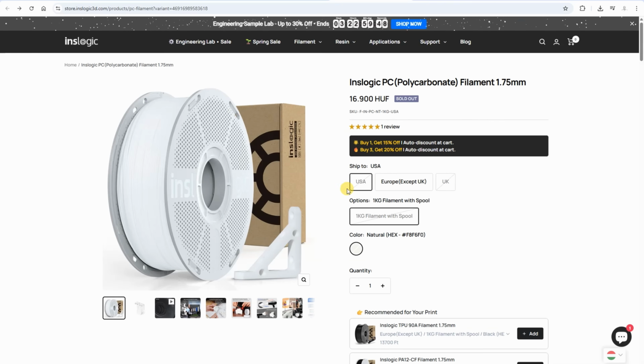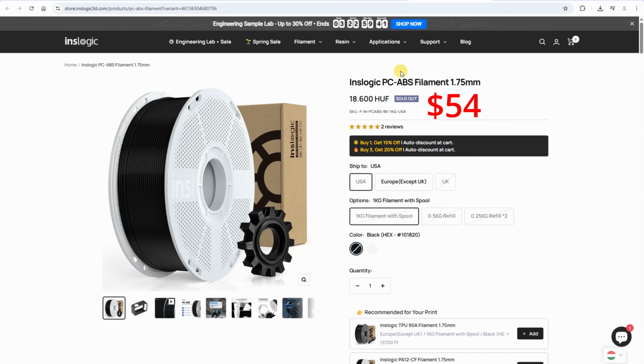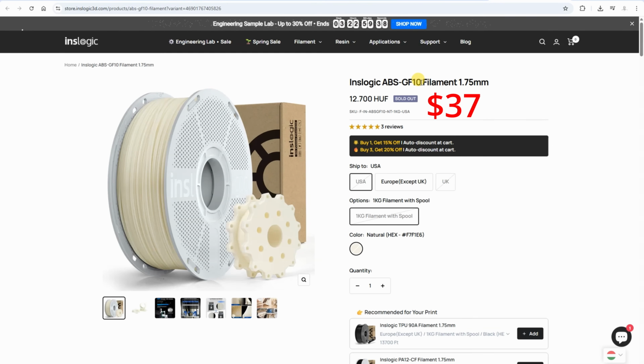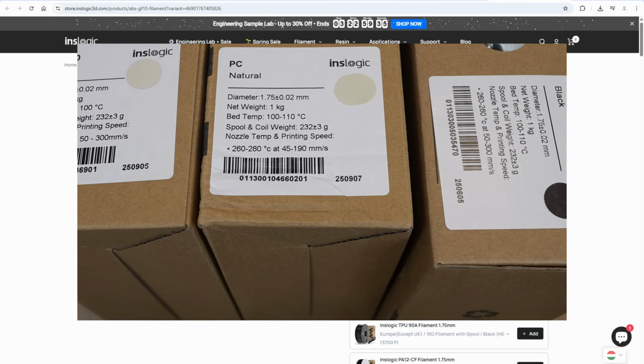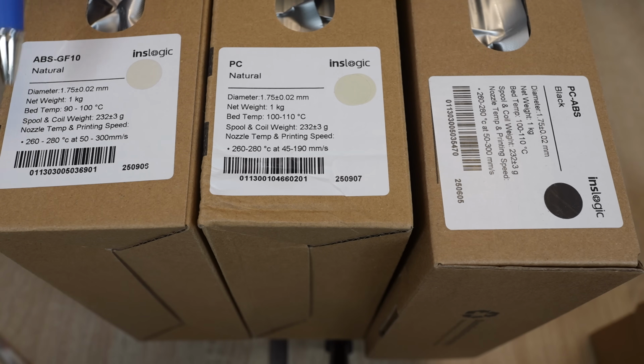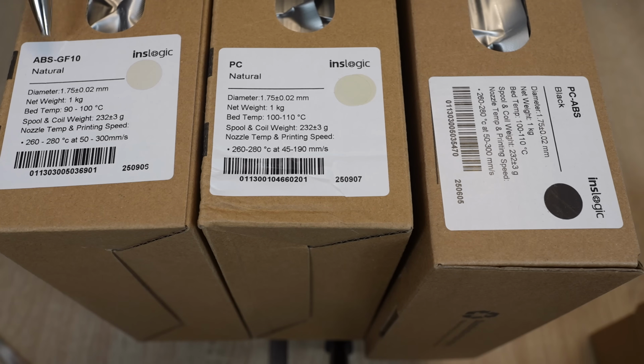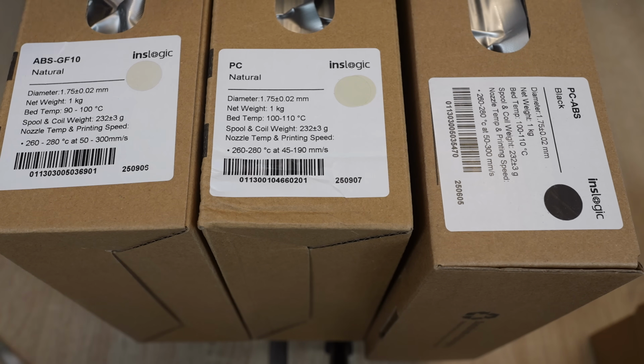The prices are approximately different for Europe or USA, and I calculated the dollars, so PC is $49, PC-ABS $54, and the glass fiber ABS is the cheapest, $37. Interesting, the print temperature range on all three filaments is equal, between 260 and 280 degrees Celsius. For these two it's okay, but usually for non-fiber-reinforced ABS it is lower. Probably here it can be higher because the glass fiber will increase the printability and overhangs should come out nice even with this high temperature, and higher temperature will still give us better layer adhesion. And nice to see that they include the information about the empty spool weight, which is 232 grams. But I'm still missing some drying information.